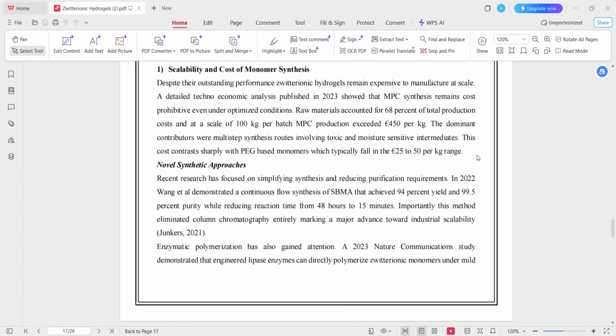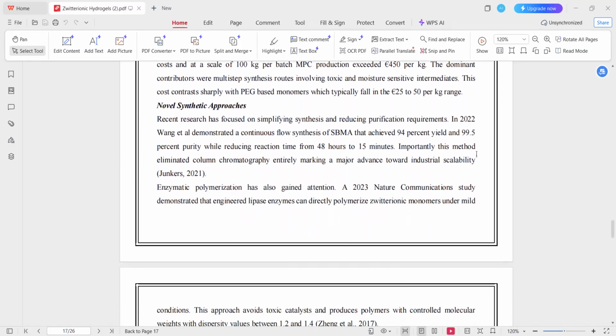In response to this cost challenge, several innovative synthesis strategies have emerged. In 2022, Wang et al. demonstrated a continuous flow synthesis of sulfobetaine methacrylate that achieved 94% yield and 99.5% purity, while reducing reaction time from 48 hours to just 15 minutes. Importantly, this method completely eliminated the need for column chromatography, which is one of the most expensive and waste-intensive steps in chemical manufacturing.